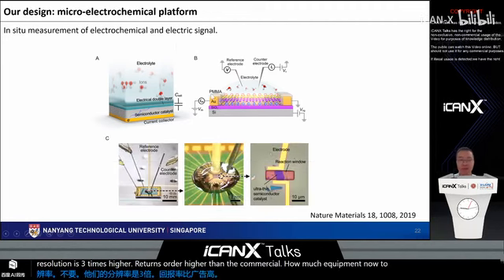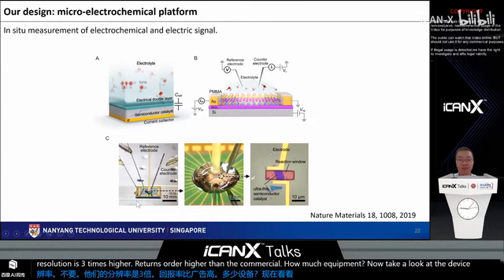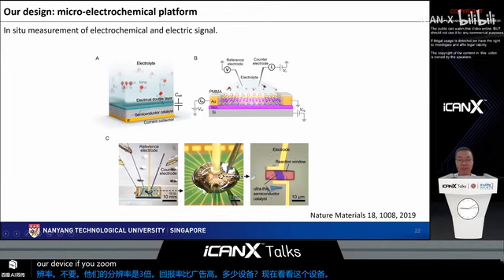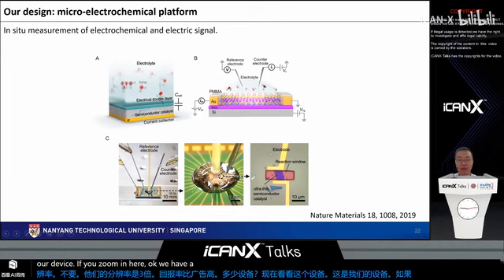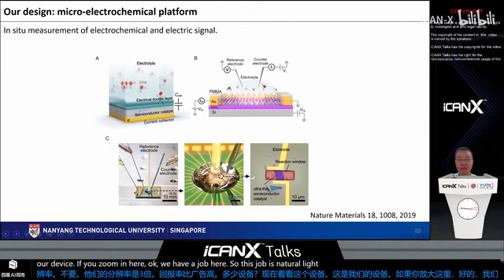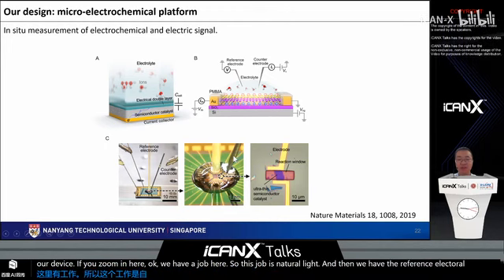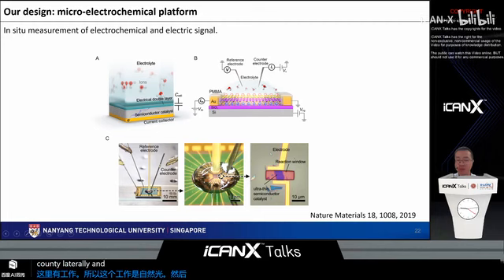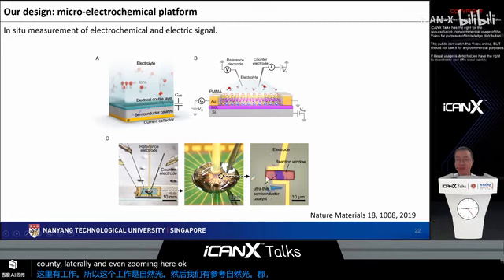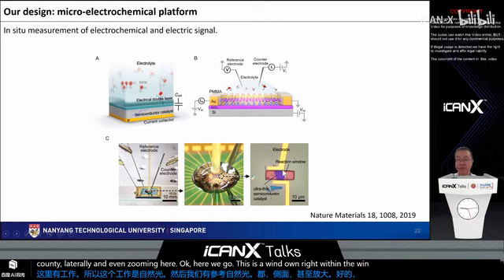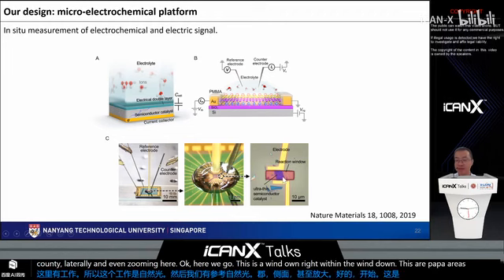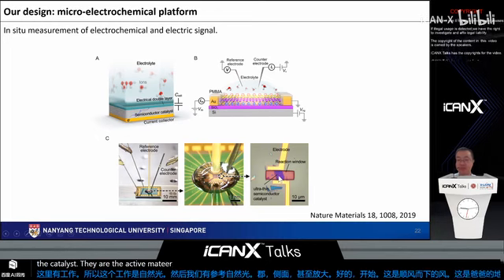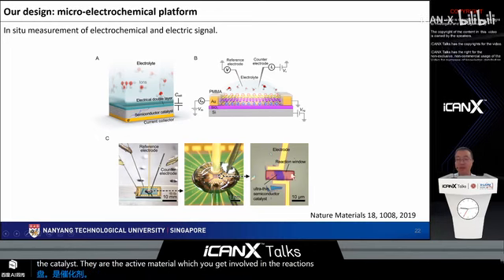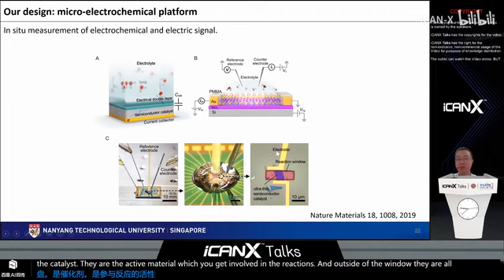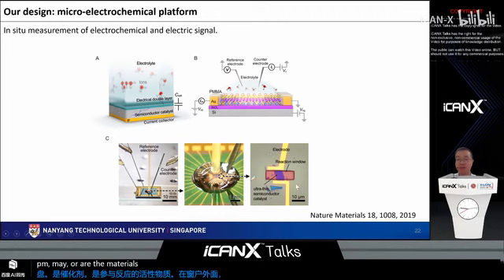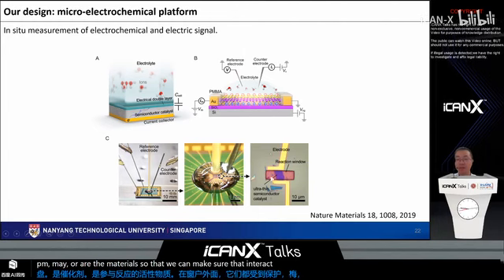Let's take a look at the real device. So this is our device. If we zoom in here, we have a drop here. This drop is electrolyte, and then we have the reference electrode and the counter electrode, and let's zoom in even further here. Okay, here we go. This is a window, right? Within the window, these purple areas are the catalyst. They are the active material which gets involved in the reactions. And outside of the window, everything is protected by PMMA or other materials, so that we can make sure the interaction can only happen in such small areas.